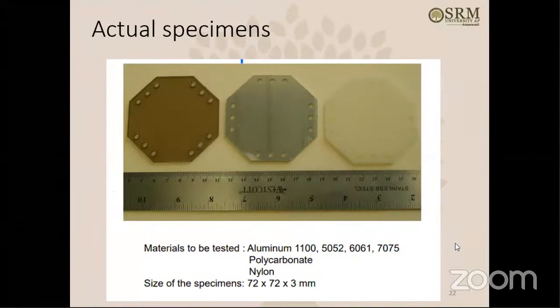So as you can see, there are different specimens. In the aluminum, we use different grades like 1100, 5052, 6061, 7075, polycarbonate and nylon, different specimens we have used. All these different materials indicate different stiffness, hardness, and yield strength levels. Okay, different material means different stiffness, different hardness, and different yield strength levels, just to collect the data and then come up with a methodology. Okay, approximate size of the specimens was like 72 by 72 by 3 millimeter.